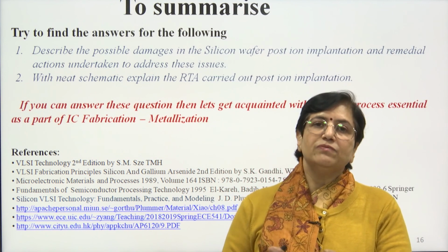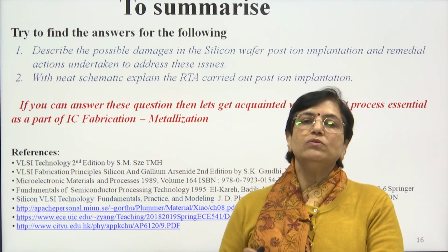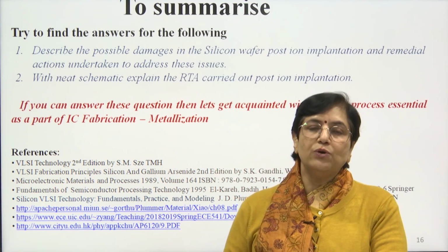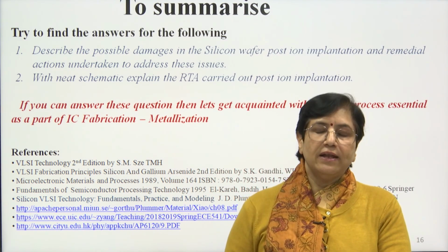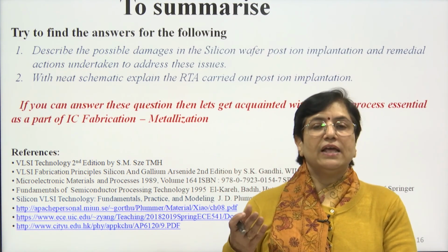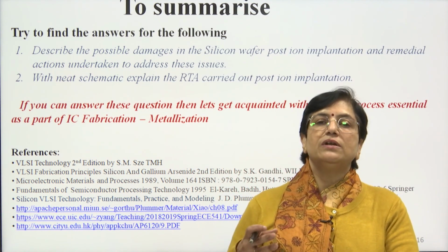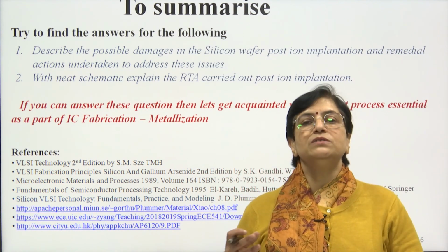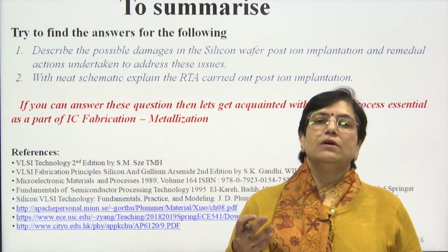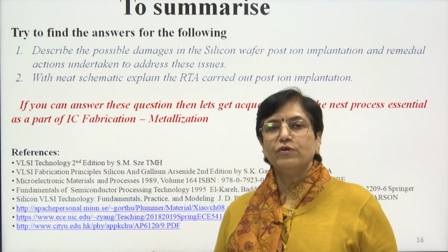There are two systems, one is furnace annealing and the other is the rapid thermal annealing system, and we saw how the profile can be better controlled in rapid thermal annealing, because the temperature can be elevated at a much faster rate, and controlling temperature and handling the contamination possibility is much easier. Therefore, RTA is supposed to be the most sophisticated and better system for controlling.